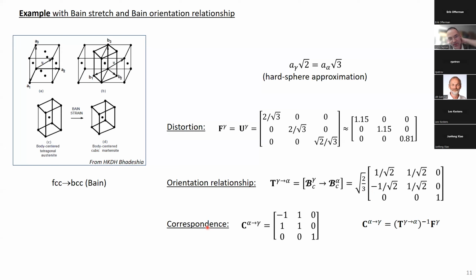On the correspondence matrix, okay, you take these vectors and you look at them after the distortion. They will become this vector here in the parent phase. So this A2 vector will become the 1, 1, 0 vector of the BCC phase. So you can get very easily the correspondence matrix. And I insist, look, here it's a stretch matrix, here it's a correspondence matrix. It is not the same. That's why when I see in some papers that people confuse the stretch and the correspondence, no, it is not the same, and we should avoid the confusion.